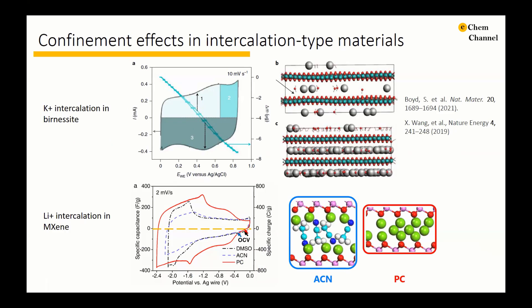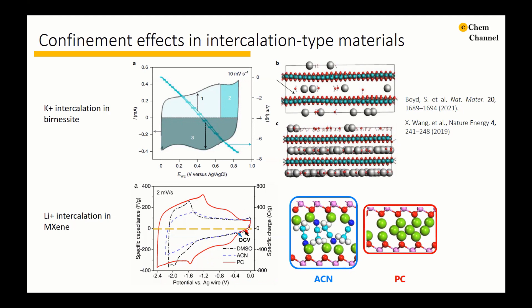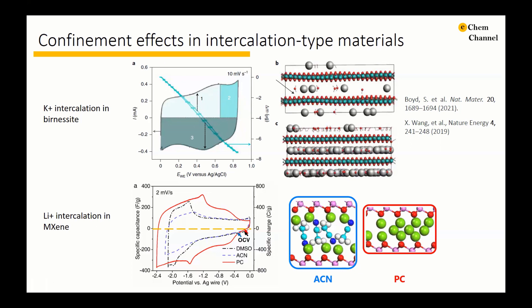Here are two examples revealing the impact of confinement on charge storage processes. Previously, it has been discussed whether the charge storage in hydrated layered transition metal oxide should be electrical double-layer or pseudo-capacitive in a neutral aqueous electrolyte. Recent studies show the varying viewpoints can be unified. Ion intercalation appears capacitive because potassium intercalates into a hydrated interlayer. Simulation further reveals that potassium intercalates directly in the middle of the interlayer, surrounded by water molecules, with relatively little structural change of the host.